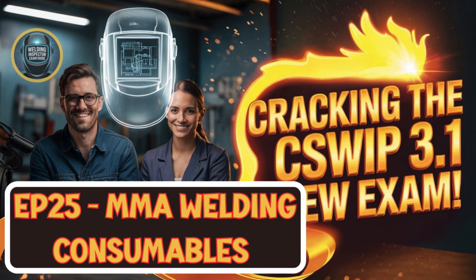Sounds powerful, but high hydrogen. Did you say that was a risk? Yes. That's the major drawback. That high hydrogen brings a significant risk of hydrogen-induced cold cracking, especially in thicker materials or higher-strength steels. So you generally wouldn't use cellulosic on, say, steels stronger than API grade X70 or on sections thicker than about 35 millimeters or so. They also don't offer great toughness at low temperatures, maybe okay down to about minus 20 Celsius, but not much colder.